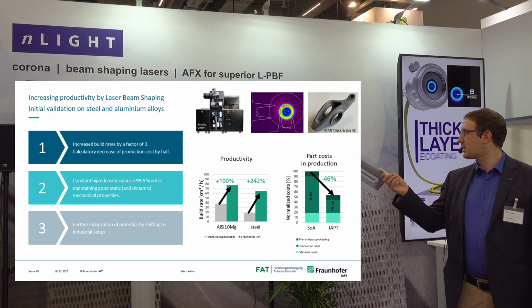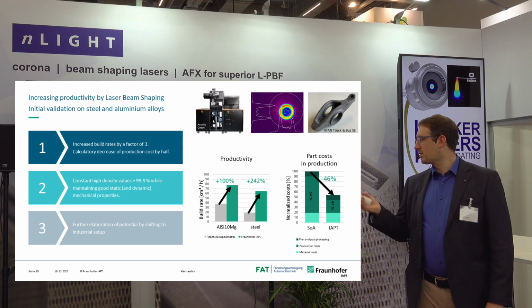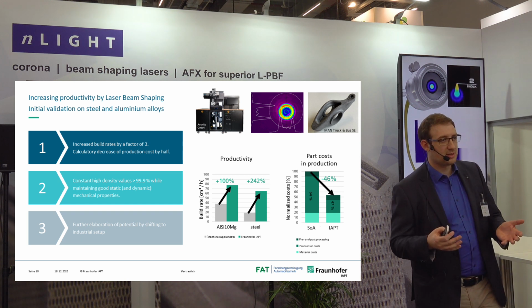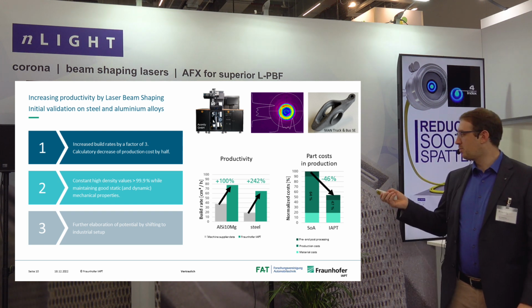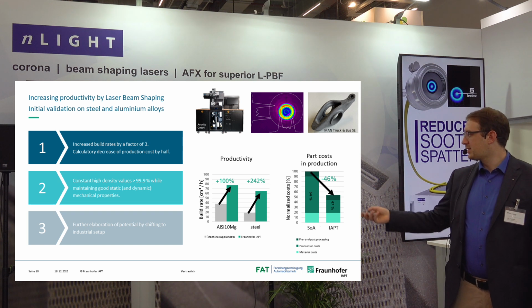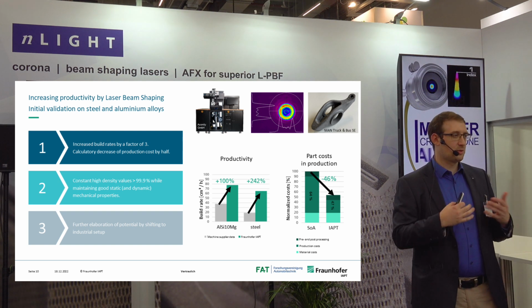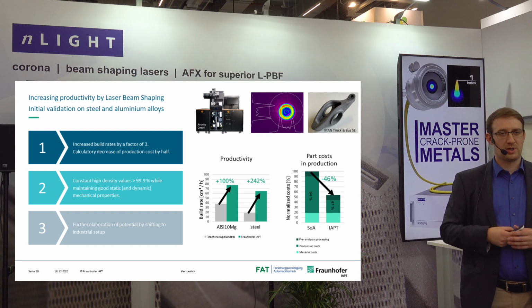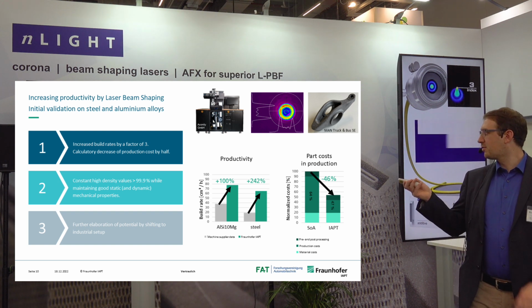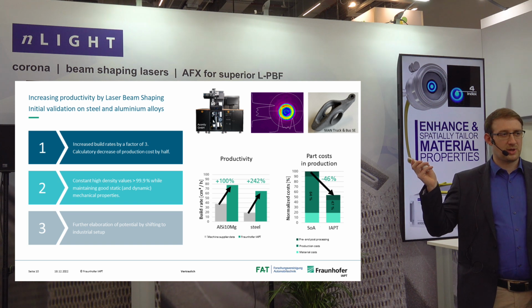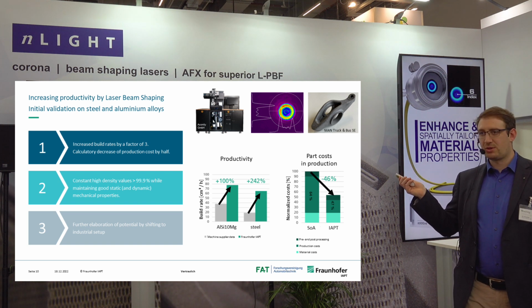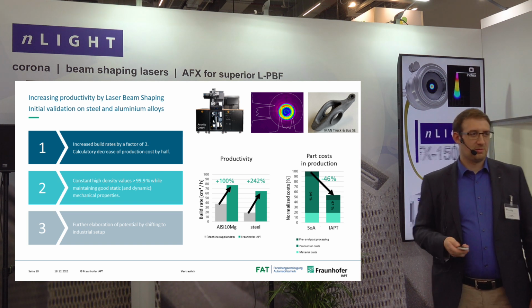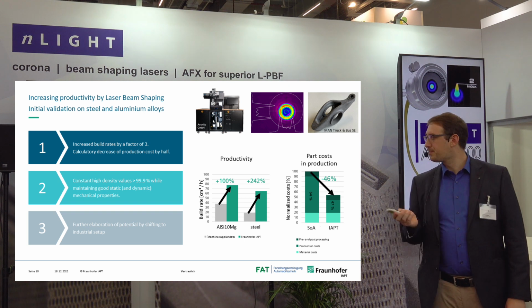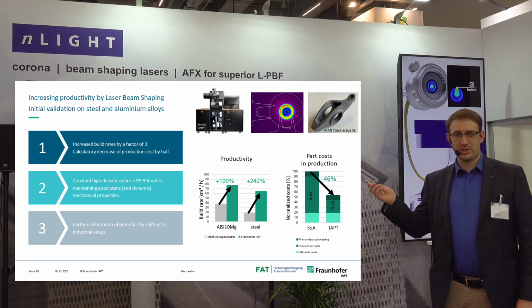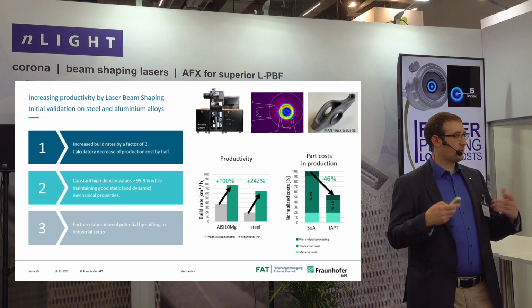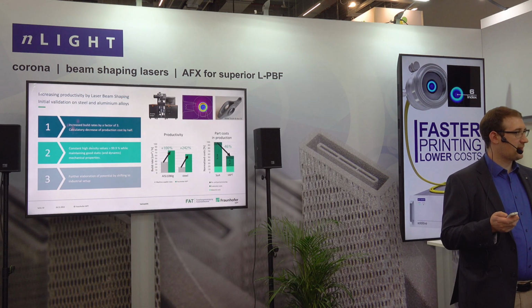So we used our lab system and looked at steel and found similar results. More impressive even, if you see in the middle graph, we could increase the productivity by 240%. And for this particular part in the top right, cost estimation about minus 46%. So this all was done on lab systems, but then the question occurs how to industrialize that.